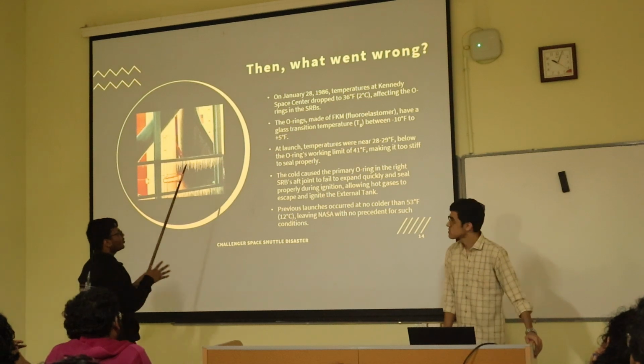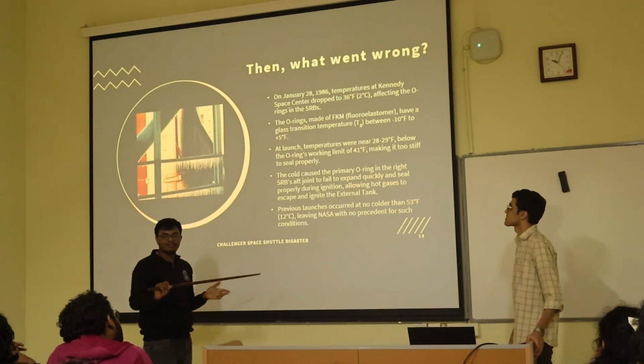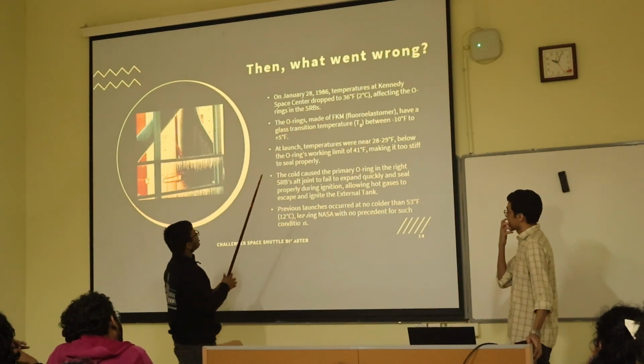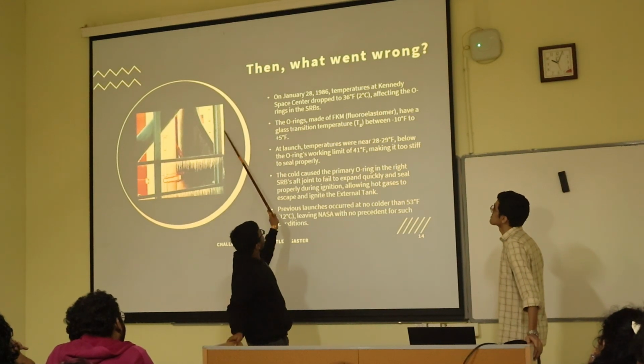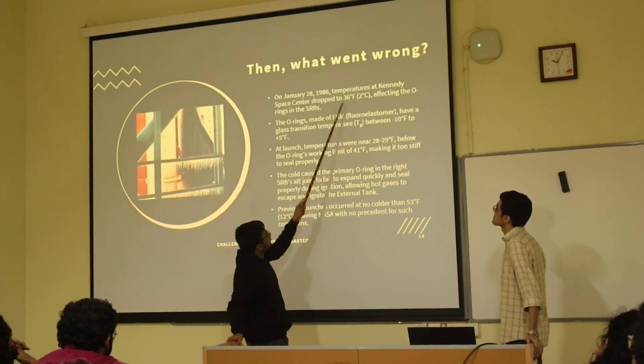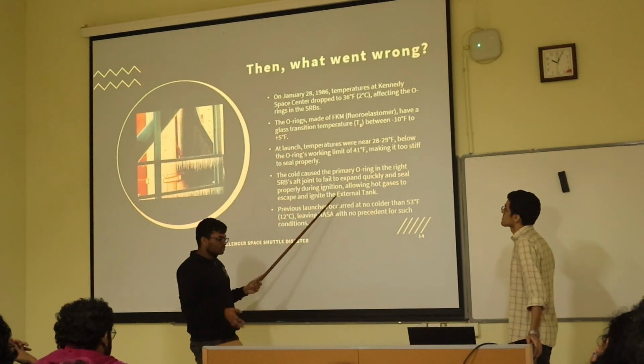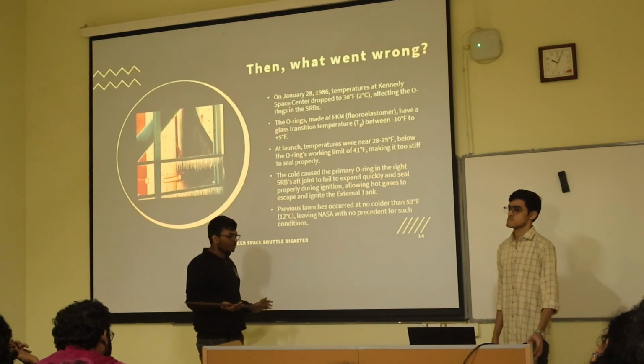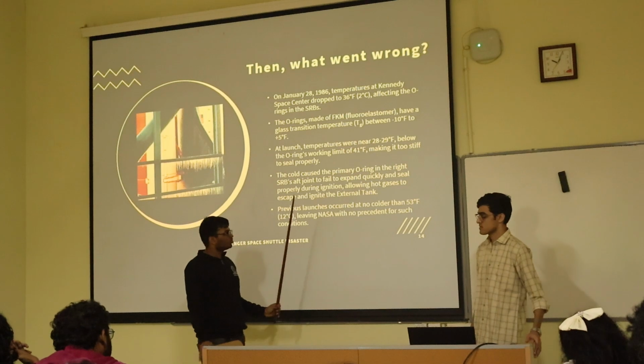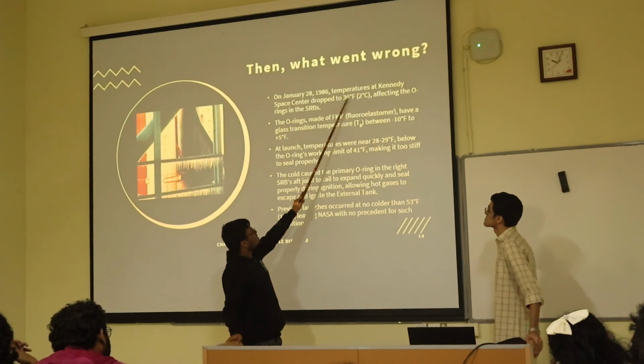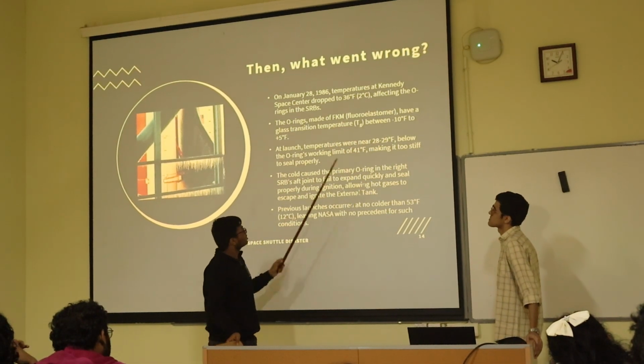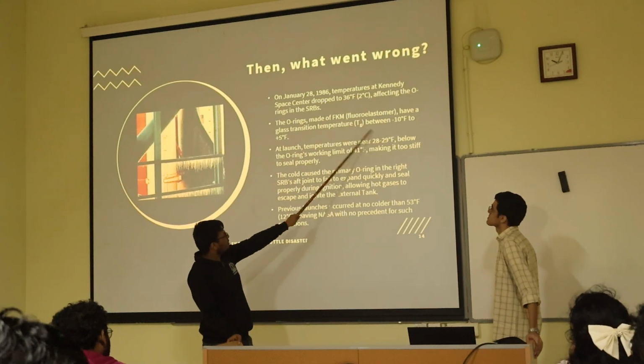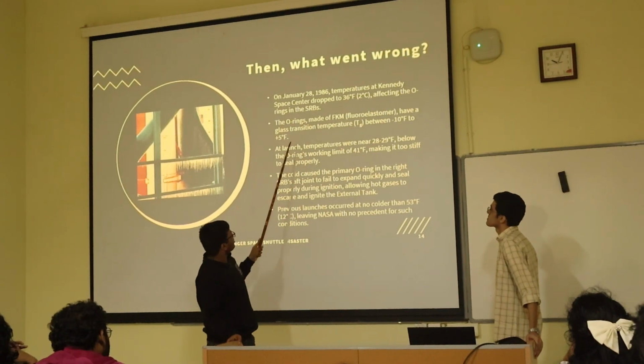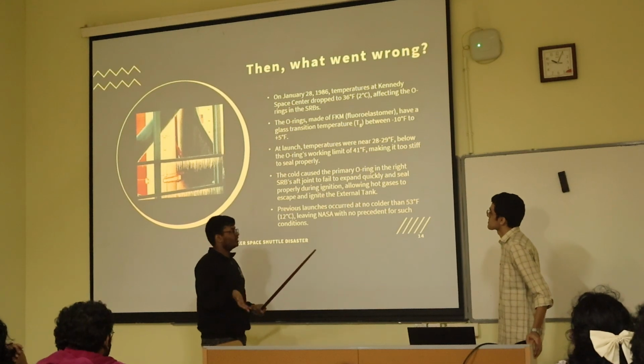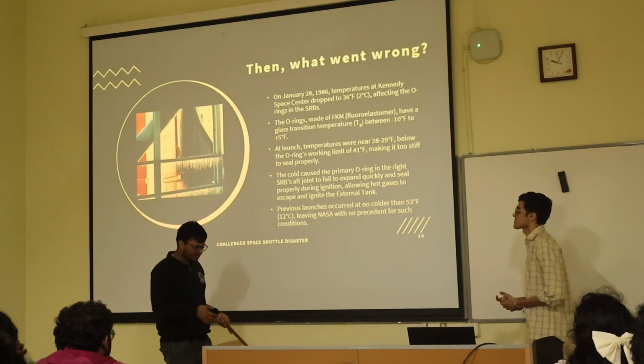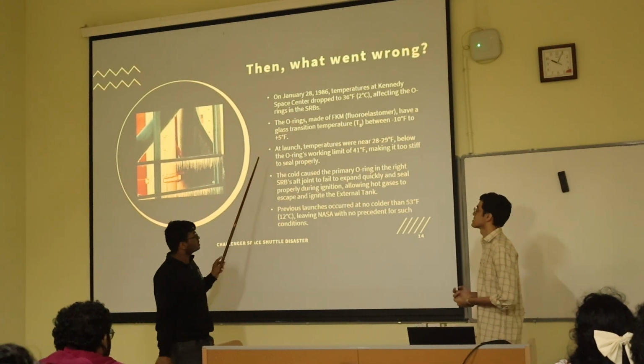So what was the main issue? I would say everything went wrong on this day. The temperature at the Kennedy Space Center dropped to 36 degrees Fahrenheit. The permissible operational limit is 41 degrees Fahrenheit, but it was down to 36 degrees Fahrenheit. And the O-rings were made of FKMs, which we'll discuss again later, and have a glass transition temperature between minus 10 degrees Fahrenheit and 5 degrees Fahrenheit, depending upon the material you choose.